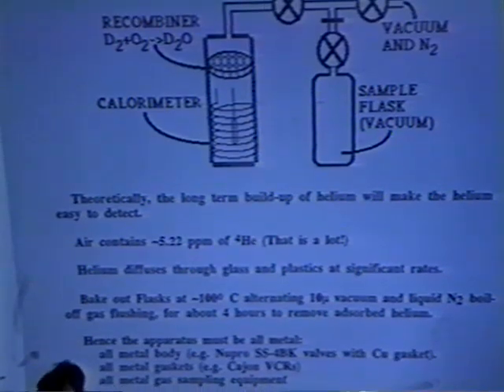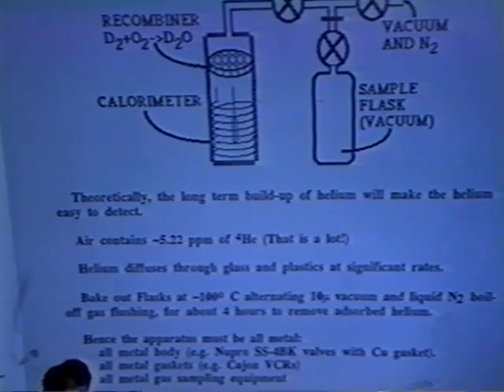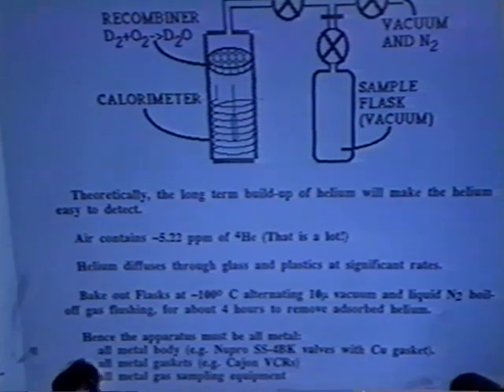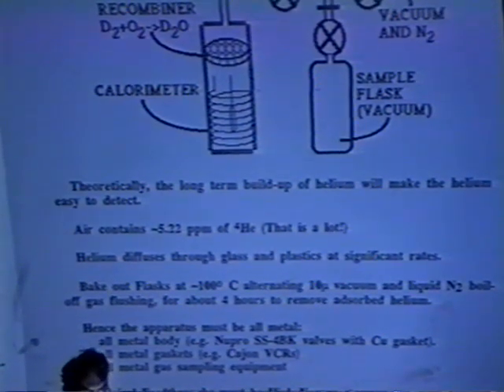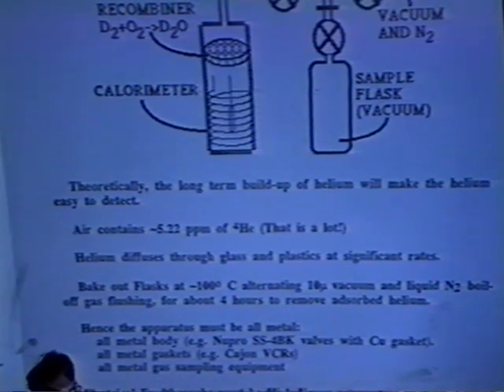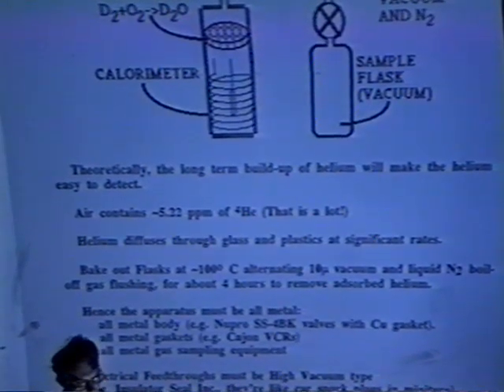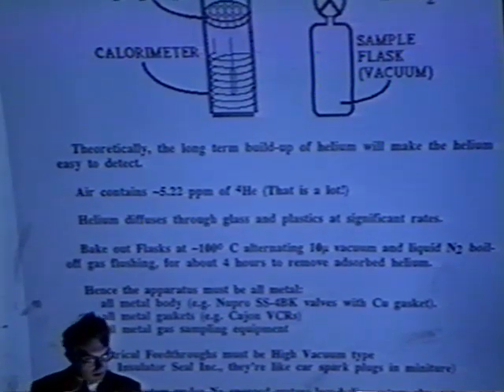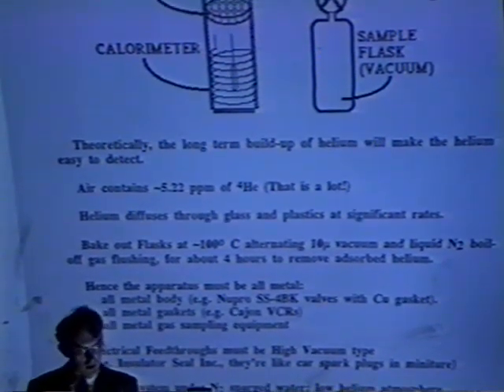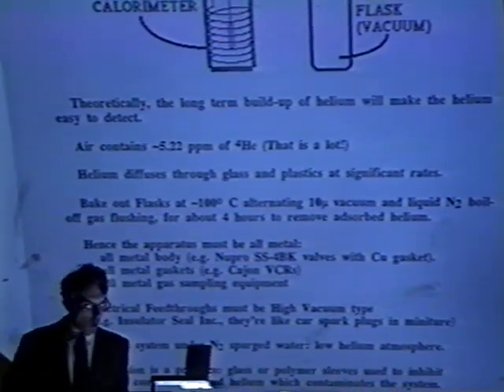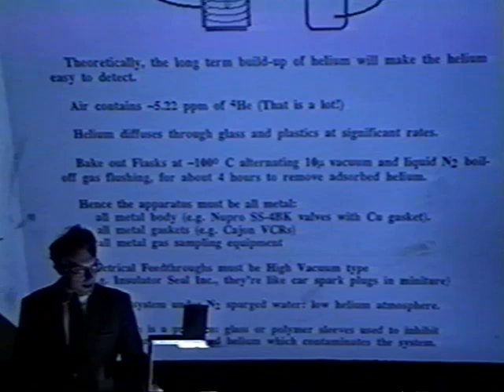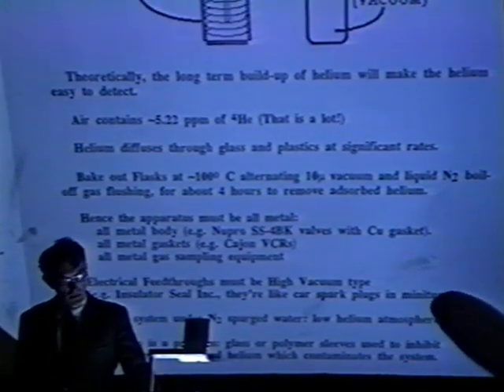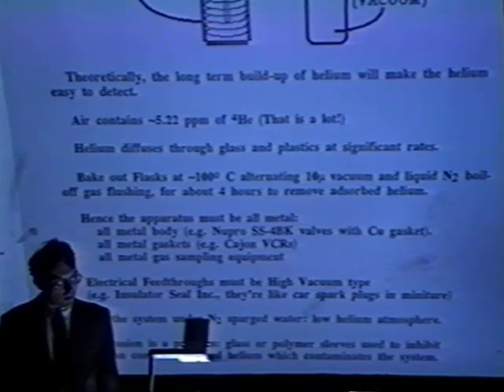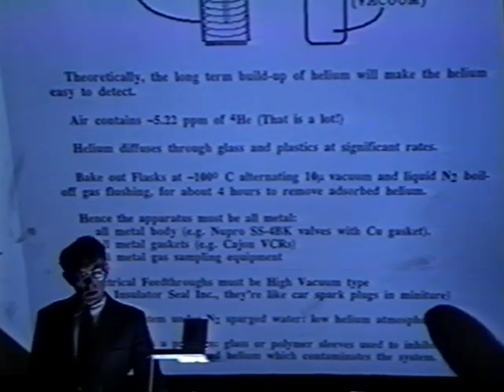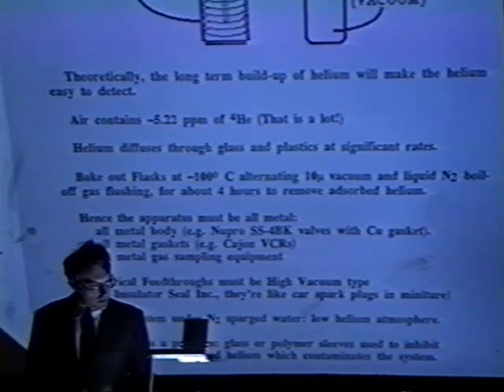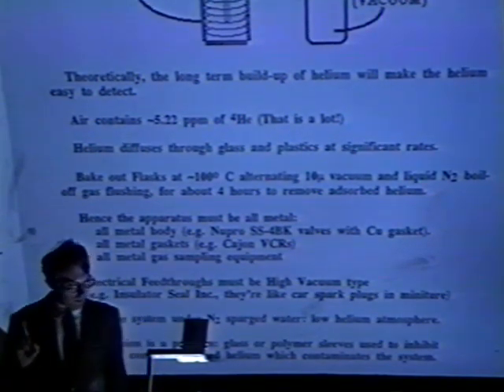So you need to make an all-metal apparatus, and for example, that means you have to have all-metal valves. You use Cajon VCRs or copper gaskets. You use expensive Nupro SS4 valves, all-metal gaskets to fit the system together. And your gas sampling equipment has to be, again, all metal. You have to flush this equipment out. Electrical feed-throughs need to be high vacuum type, insulator sealed, incorporated type stuff. They're like spark plugs. They're ceramic electrical feed-throughs. They're quite small, and they will keep the helium out too.